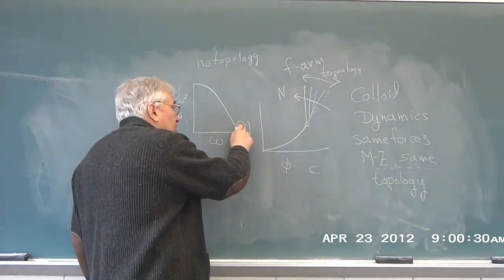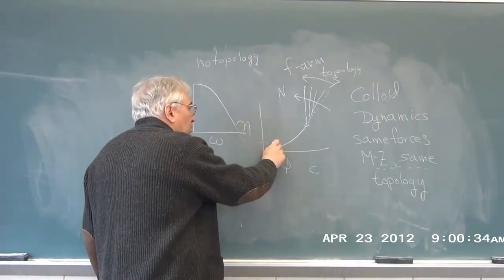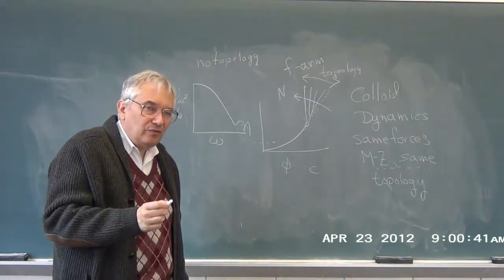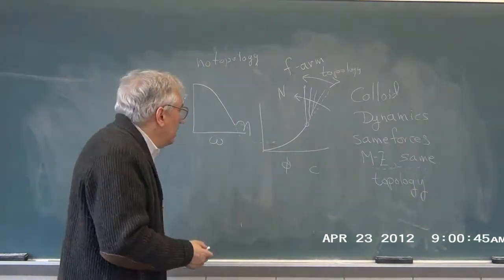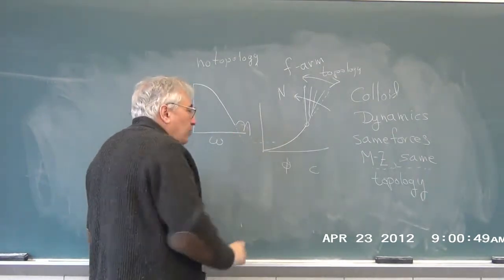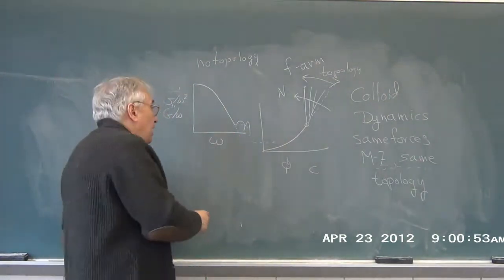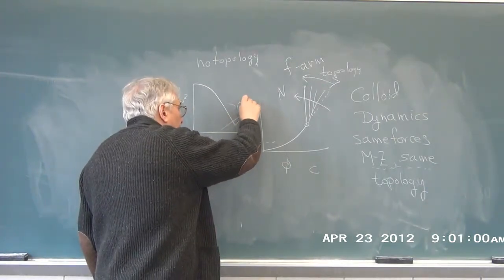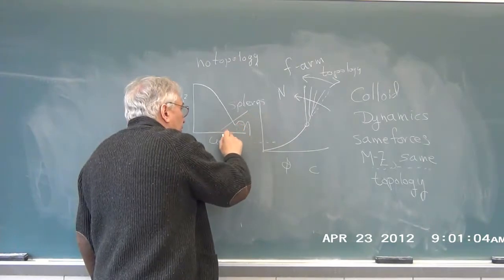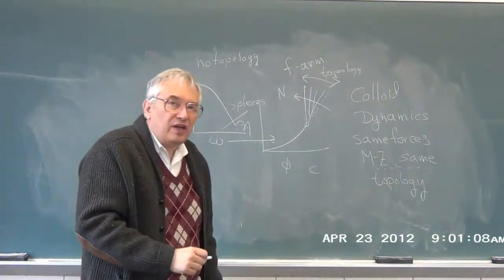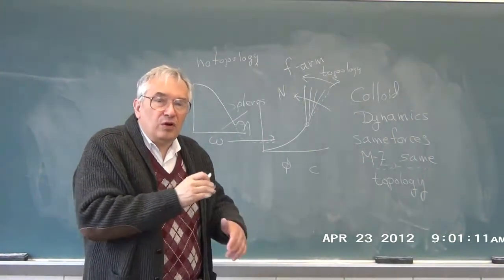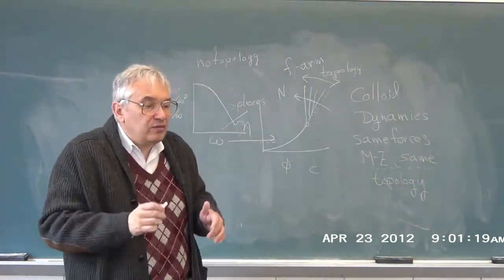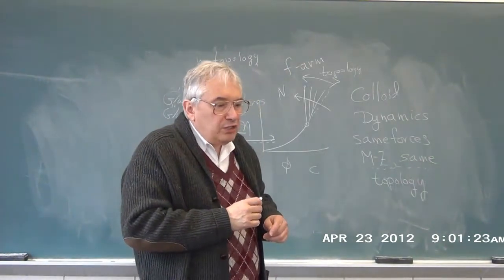If you do this for polymer coils and you go out far enough in frequency, you see a rollover or you see bumps that do various things. That's not seen for hard spheres. However, if you look at the numerics, polymers have been carried out to much higher frequencies using time-temperature superposition. And it might be the case that if you took hard spheres and did the studies over a much wider range of frequencies, you would start to see exactly the same effect you see for polymer coils. That is, the sphere measurements were not carried out as far in frequency, and therefore you don't want to say there's a topology difference here because it's not clear that you've actually looked at it. Okay, what else can you do?